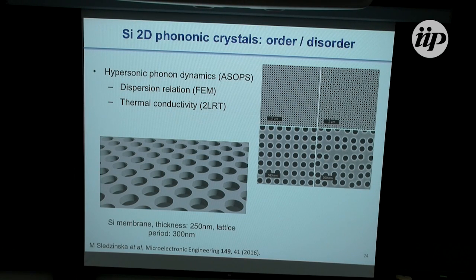So the frequency regime that we will look at is the hypersonic regime. Experiments are by asynchronous optical sampling spectroscopy, which is a type of pump and probe. We calculate the dispersion relations by FEM, and we measure the thermal conductivity by two-laser Raman thermometry. Typical samples, 250 nanometer, lattice period about 300 from center to center. And here you have the order and the disorder, the positional disorder one.